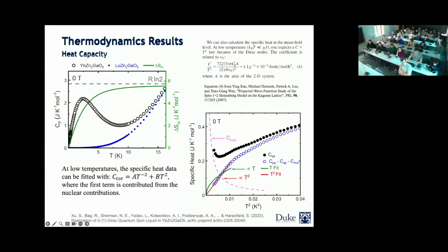Can I just clarify that a bit more? In order to subtract that divergent contribution, it's a 1 over T squared. T squared, yeah. You need a concentration of isotopes and you need g factors. Is that right? That's right. Maybe it's a question: can those be measured independently? So it's not a fit, just a fit-free subtraction, or do you actually fit it? No, we actually fit it and subtracted it. But the value for A is in agreement with the values that other people have found on different ytterbium compounds. So that's our indication that most likely it is in agreement. And then I will show you more of this analysis with the field dependence as well.